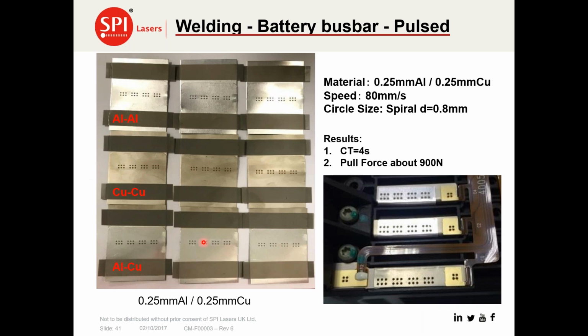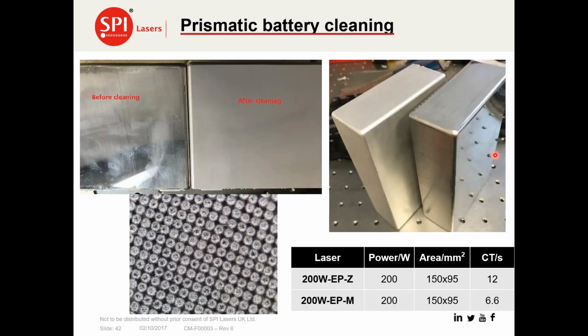All of those are possible using the 200 watt EPZ nanosecond type laser with good pull forces, and again, reasonably high speeds. We use these spiraling techniques to create these larger spots, and we can effectively make the spot size as big as you want. Although actually, if you go too big, you end up putting in too much heat. So the technique is to use multiple small spots to get the best productivity, interface area, and control of heat input.